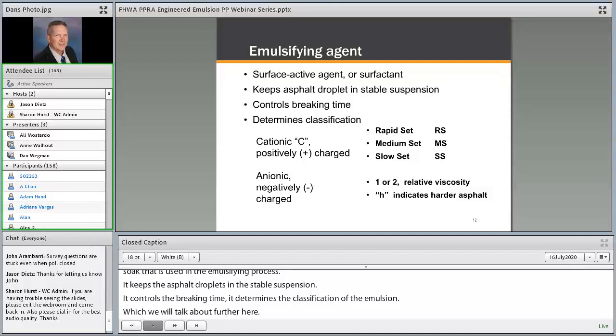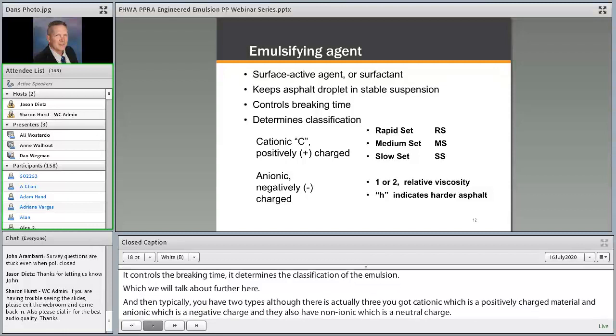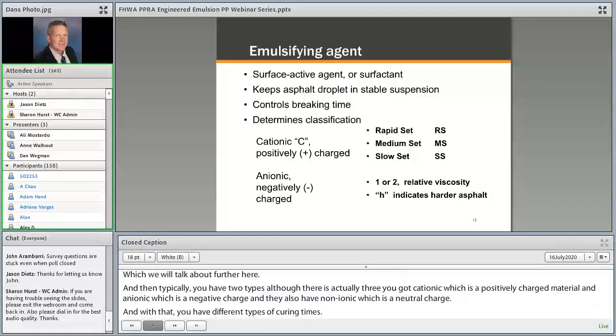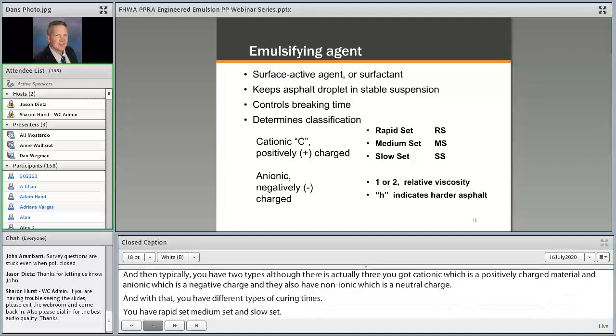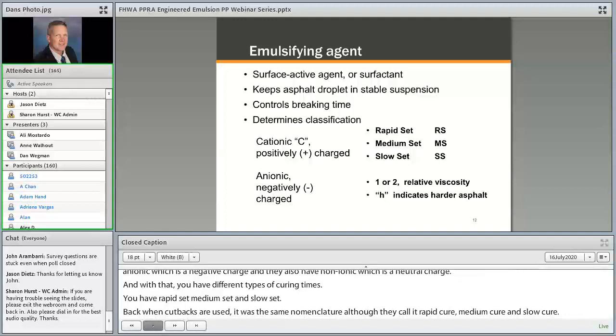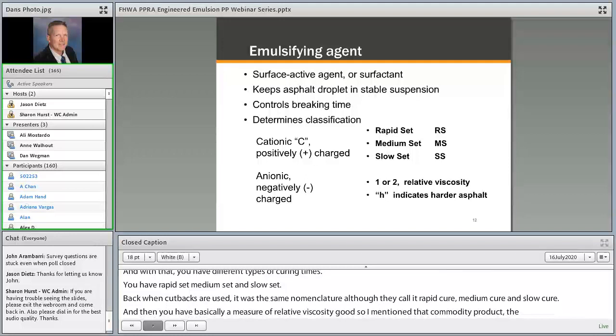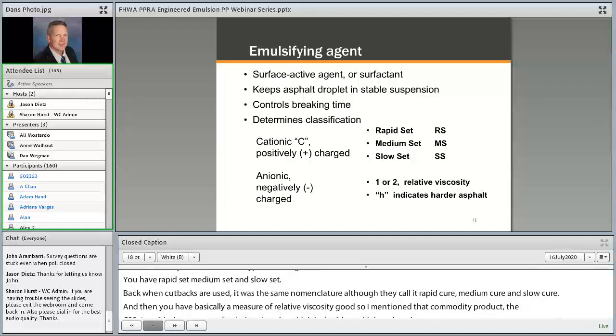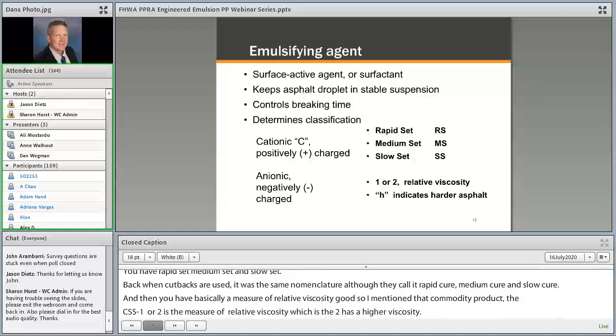And with that, you have different types of curing times. You have rapid set, medium set, and slow set. Back when cutbacks were used, it was the same nomenclature, although they called it rapid cure, medium cure, and slow cure. And then you have basically a measure of relative viscosity. So I mentioned that commodity product, the CSS1 or CSS2, basically is a measure of relative viscosity with the 2 meaning it has a higher viscosity. And then the H at the end indicates that a harder asphalt is used. And we'll talk about selecting the base asphalt for making the emulsion a little bit further.